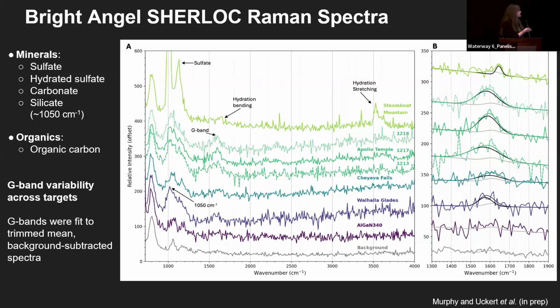We also saw a feature around 1600 that's marked here as the G band, and this is consistent with organic carbon. Down below here, we analyzed our AlGaN calibration target, and this was to serve as a negative control because we don't expect to see an organic carbon signal here. And the very lowest one in gray, this is our instrument optical background signal.